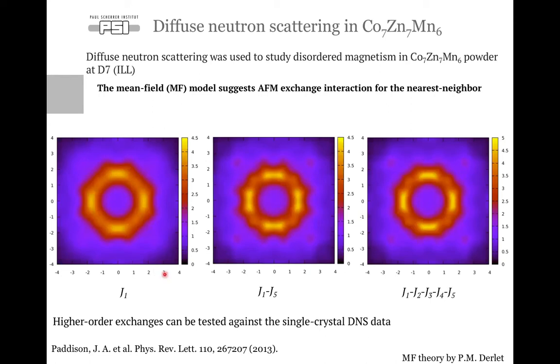However, it would be interesting to measure single crystal diffuse neutron scattering data to see whether the higher order contributions, for example J1, J5, that are shown to be quite important for the parent beta-manganese compounds, can actually contribute to the short-range correlations, or whether antiferromagnetic exchange between neighboring manganese ions is enough to explain the single crystal data or not. Additional measurements on diffuse neutron scattering with single crystals would be required to reliably distinguish between these different theories.